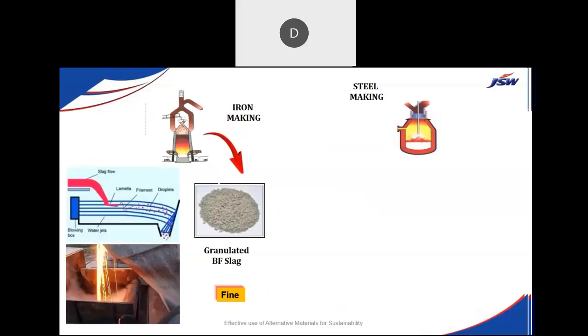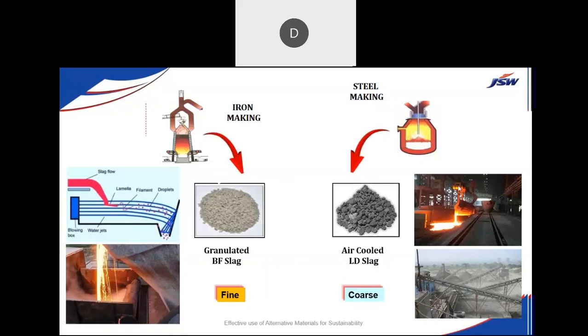And the moment slag comes out of the blast furnace, we use a good cooling technology, chilling technology, to get granules. The granules are very glassy in nature. They can be crushed into fine powder to make GGBS, which can be used for cement making also. And if you don't convert into a finer material, you can make slag sand out of it. Using air-cooled LD slag, we can make aggregates, coarse aggregates.